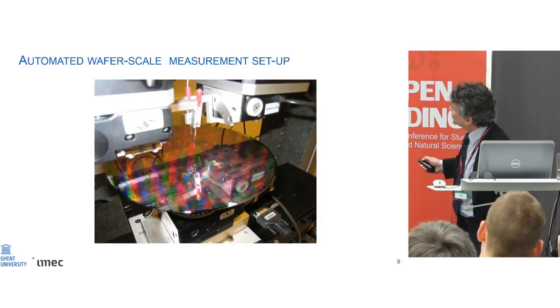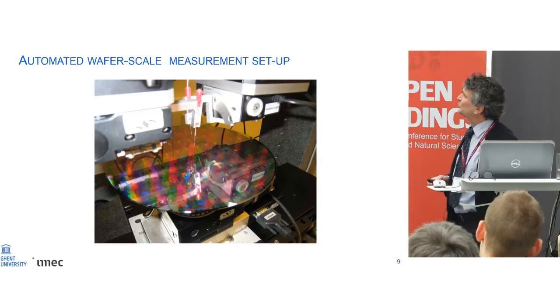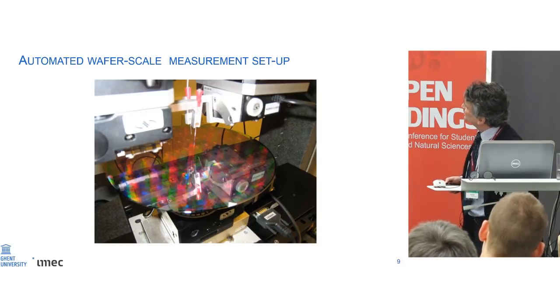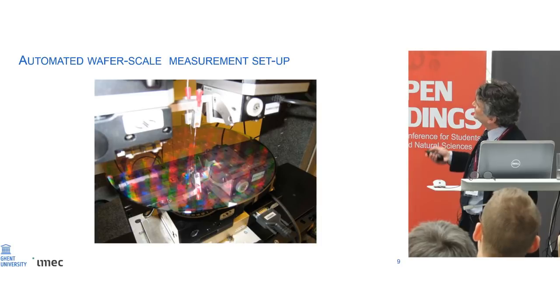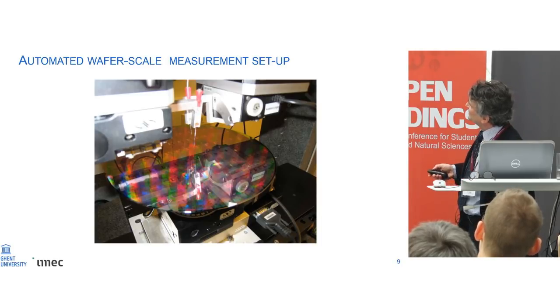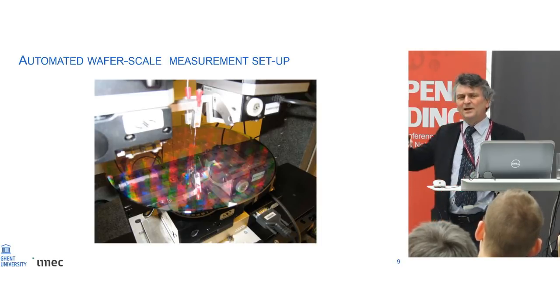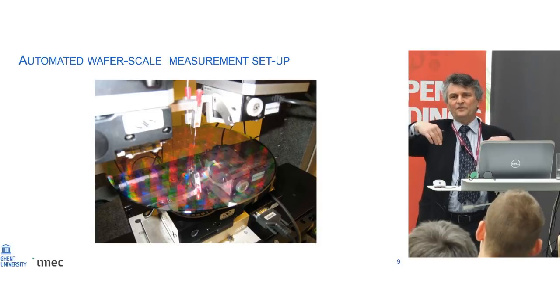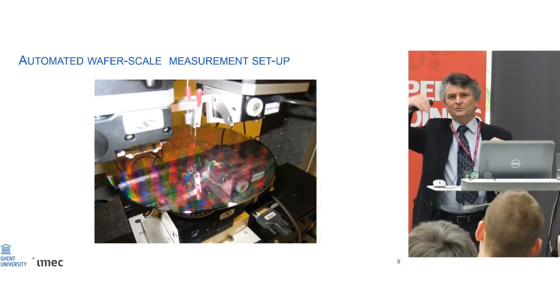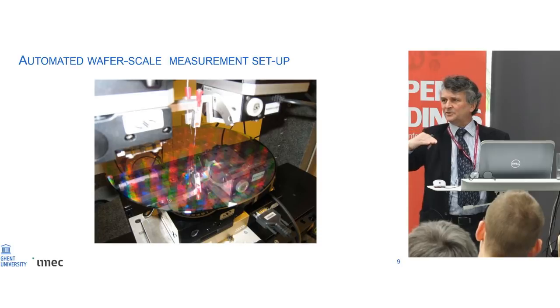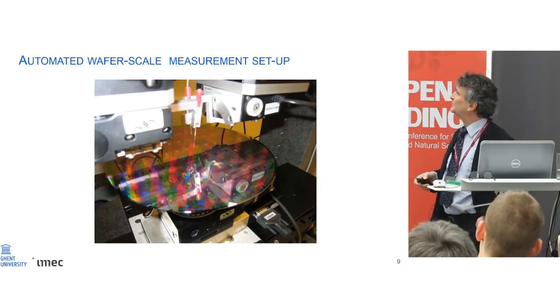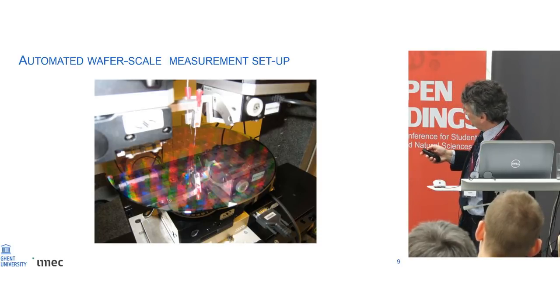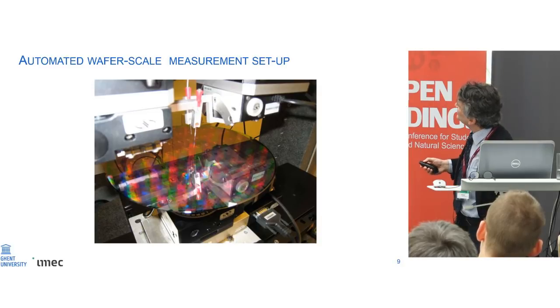And these are made on large wafers, of course, that drives down the cost of making such chips. This is a 200 millimeter wafer. And actually, we do even automated wafer level testing. What you see here is that we couple light in from an optical fiber from above, and through a little diffraction grating, we couple light from the vertical fiber into the plane of the waveguide. And with that, we can do wafer level testing, and that is actually visualized, if all goes well.